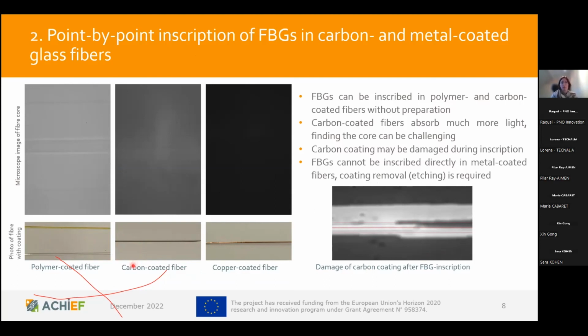We need the carbon coating because we need a way to actually deposit then the metal onto the fiber. You've seen that in the schematic layout of our experiments. And the carbon is weakly conductive and supposed to help our metal deposition after the FBG inscription setup.